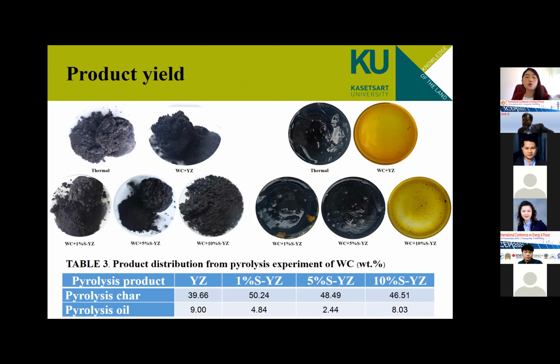Okay, this picture shows product yield. Product yields are pyrolysis char and pyrolysis oil. Looking at Table 3, you can see the yield of pyrolysis products. It was found that the amount of pyrolysis char was high, while the amount of pyrolysis oil was relatively low. Generally, the main component of waste cable was polyvinyl chloride or PVC.